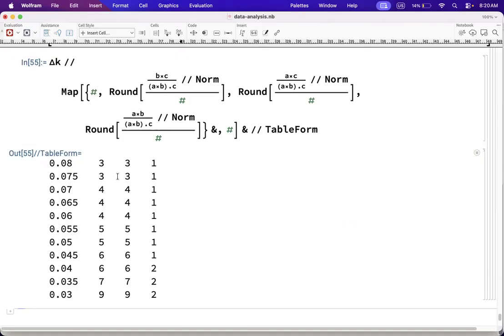In fact, if you use a bigger one, you might say it increases the precision. But it's not correct, because you'd be trying to capture the interaction between the slabs, and that is the problem. That's the reason we use a 1 in this dimension. Even though here I showed you that it is 2, we're going to check 2, 1, please. Okay. Questions in here, please? Questions? Okay, I'm going to pause.